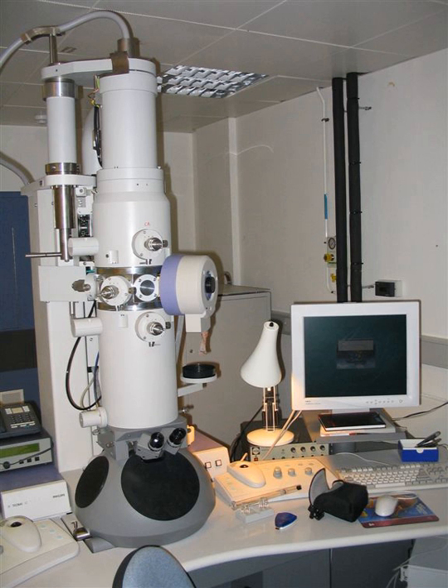The specimen is returned to room temperature and pressure, then the extremely fragile, pre-shadowed metal replica of the fracture surface is released from the underlying biological material by careful chemical digestion with acids, hypochlorite solution, or SDS detergent. The still floating replica is thoroughly washed free from residual chemicals, carefully fished up on fine grids, dried, then viewed in the TEM.